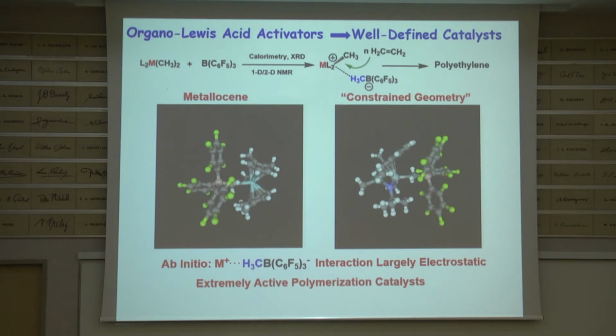So what happens is there's a series of olefin insertions, very, very rapid, very exothermic, and there's always a competing reaction. It's called chain transfer. And every so often, rather than propagating by insertion, there'll be an elimination reaction to produce a polymer chain with an olefinic end group, and then a new growth will begin.